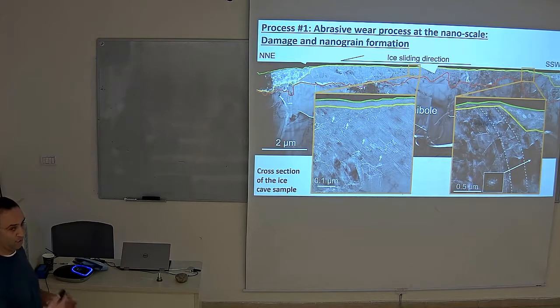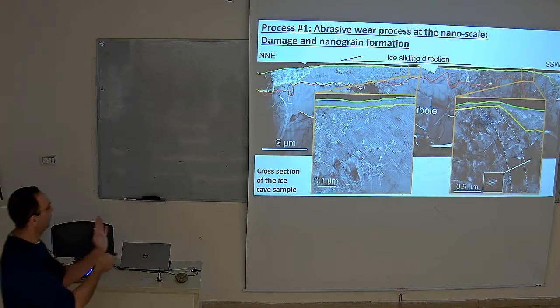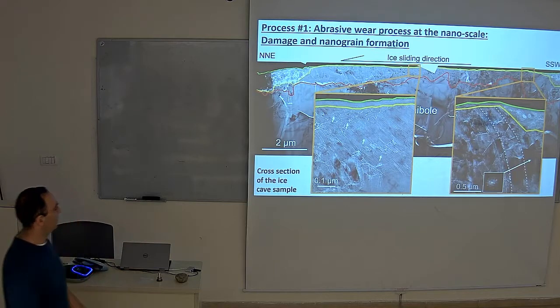So this is a real observation of the formation of nanoparticles just by this mechanism of crushing and having denser joints, denser fractures in the rock. So we have the material to form a coating layer. Now we see the start of this coating layer here in the margin of this cross-section, between the yellow line and the green line. It's a kind of breccia.